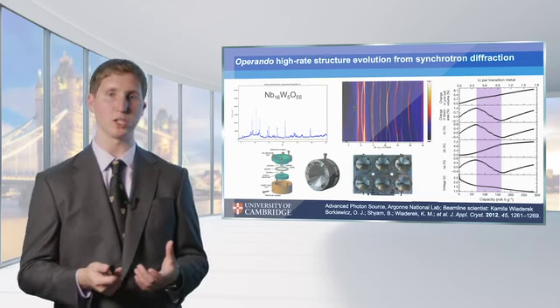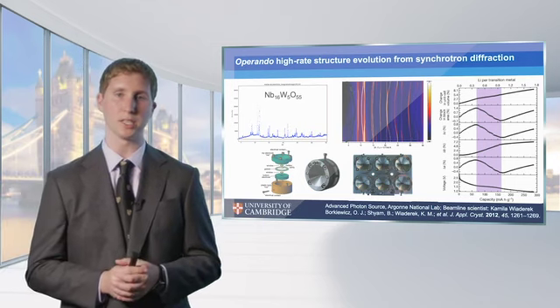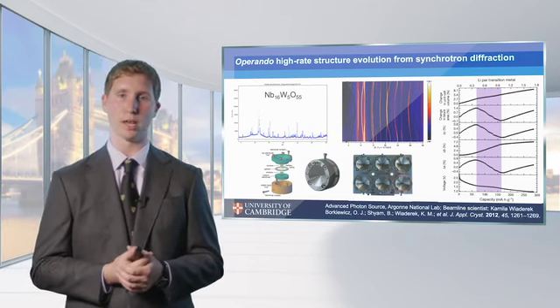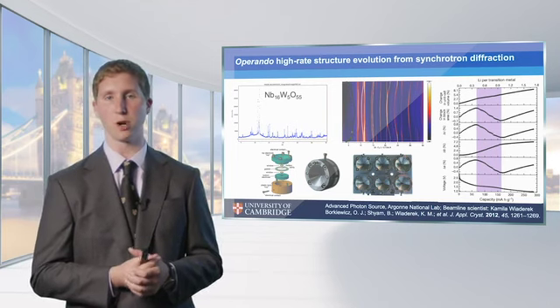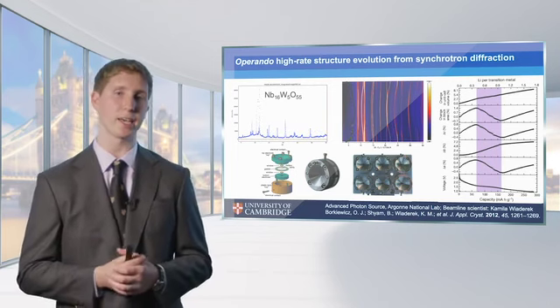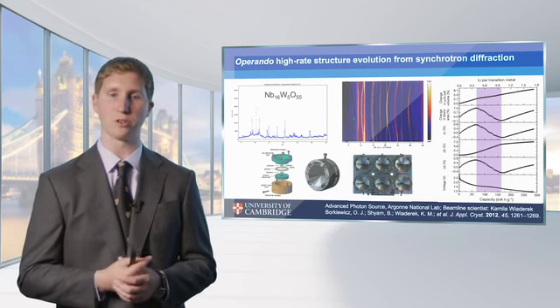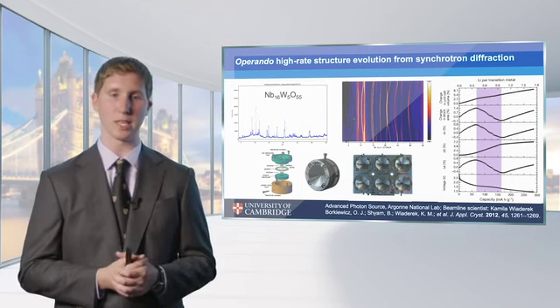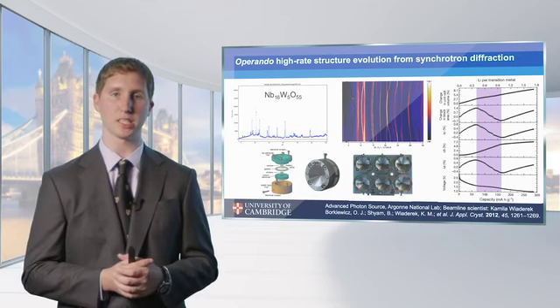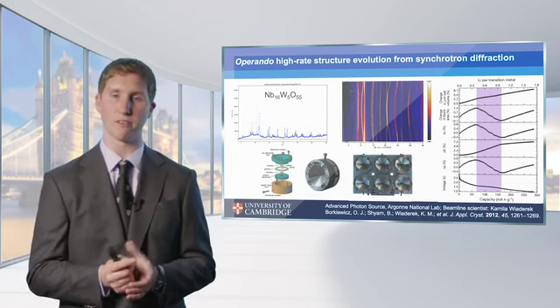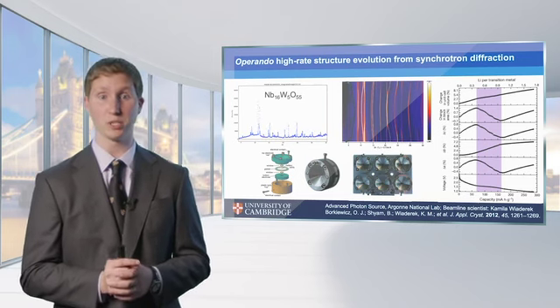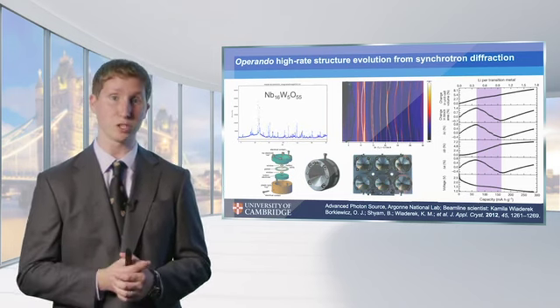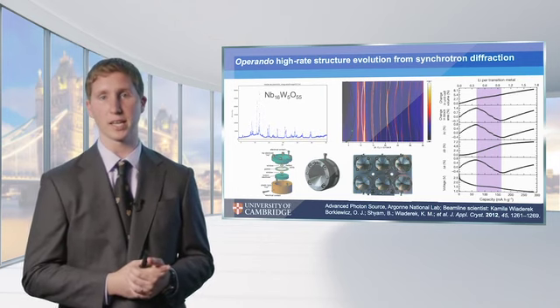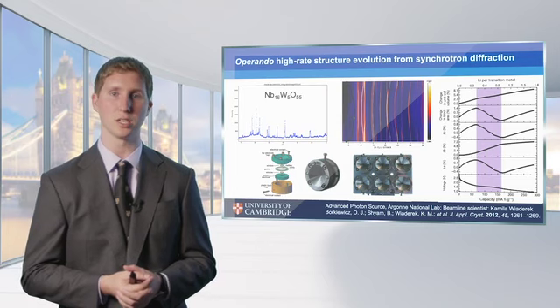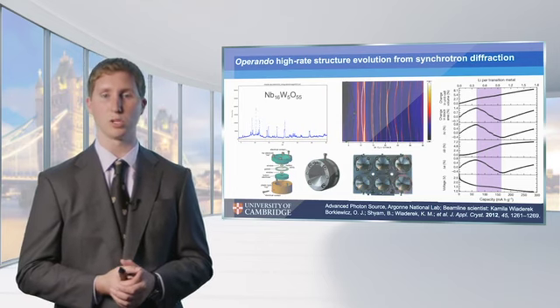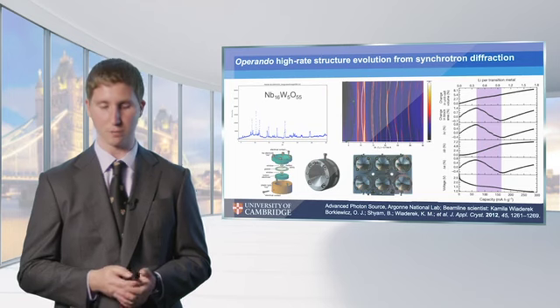And this small volume expansion is great because it minimizes the strain on these particles. And that also allows us to use these large 5-10 micron particles without observing significant cracking over thousands of cycles. When you fully lithiate something and have a large volume expansion, so say in the case of silicon as an advanced anode material, which has a several 100% expansion in its volume compared to the 5% we're observing here, then you get significant cracking. And that particle cracking makes it very hard to stabilize the structures for many cycles, which is important as we're trying to achieve many thousand here.